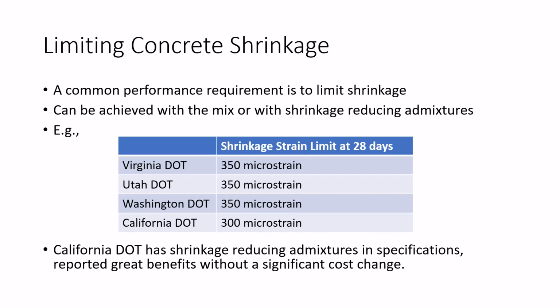From a few participating states, their shrinkage strain limit at 28 days is right around 300 and 350 microstrain. How they achieve that is kind of up to them. For example, California DOT uses shrinkage reducing admixtures, but it's an optional thing. So if you can achieve that shrinkage strain without admixtures, then that's okay too.